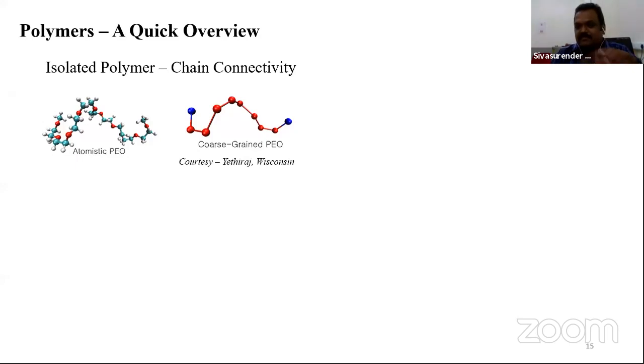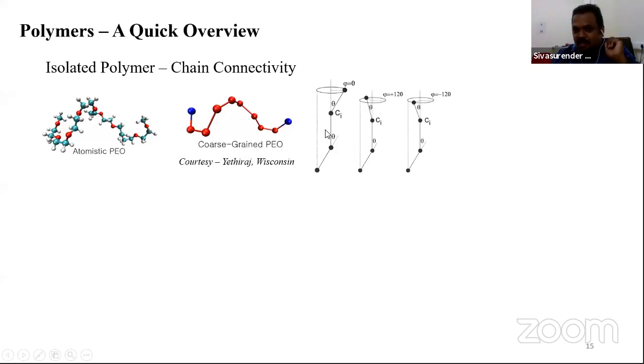And now at this level, you can think of various degrees of freedom, starting from fluctuation of bonds, fluctuation of the moieties, and more important degrees of freedom, like the torsional degree of freedom. To let you realize what it means, here I show you a snapshot of a small piece of a polymer, which shows just 3 different bonds. The angle between the first 2 bonds is defined by the bond angle because of quantum mechanical reasons, right? And now the moment you go into the third bond, while the bond angle is fixed, it can occupy any position in the entire 360 degrees of this torsional freedom, right? That gives a huge entropy for these polymers. And at this level, all these different degrees of freedom essentially dominate the behavior of polymers.